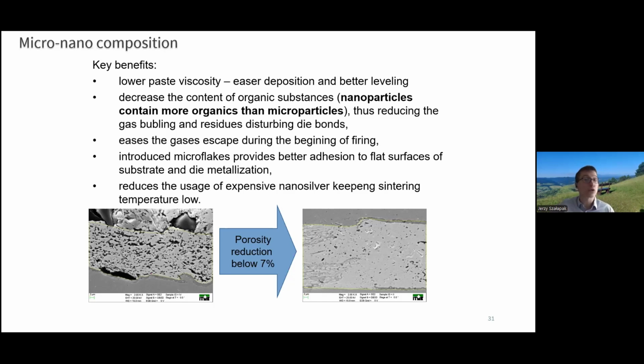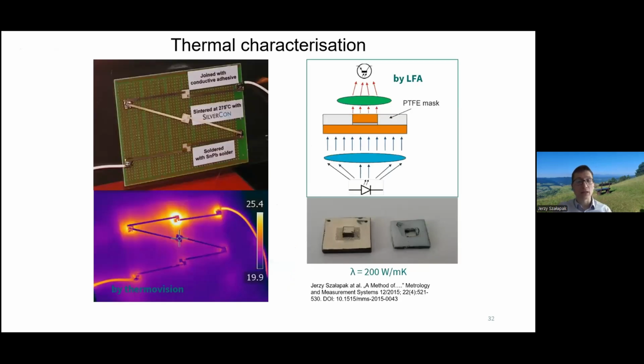With that, we lowered the content of organic substances acting as a coating and lowered the overall cost of the material. And we achieved shear stress resistance of 20 plus megapascals, so comparable to solders, and electrical resistivity 5 times better than soldering, with only 2 times higher resistivity than for bulk silver. The joints were tested not only electrically, but thermally. Thermal analysis was conducted with laser flash analysis and a comparative method, and then we confirmed it with theoretical simulations based on the Wiedemann-Franz law. Thermal conductivity was also about 5 times better than for lead solders, at about 200 watts per meter Kelvin.